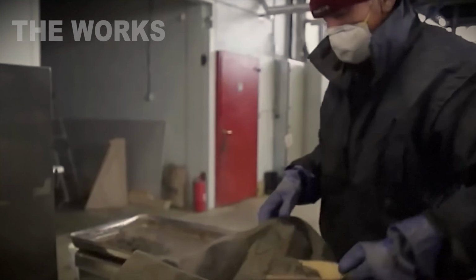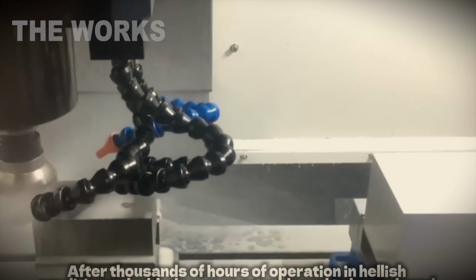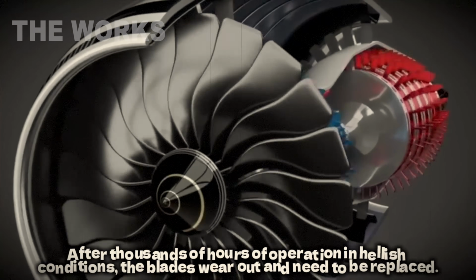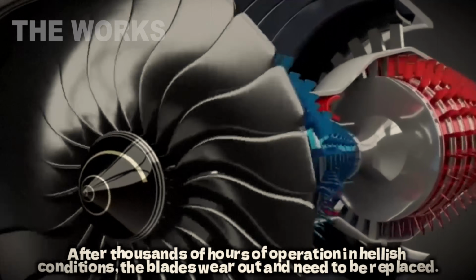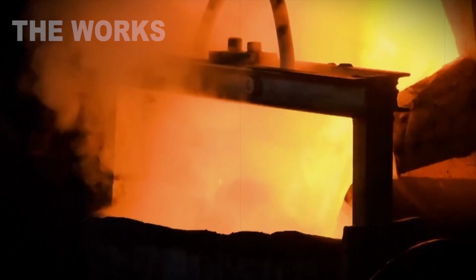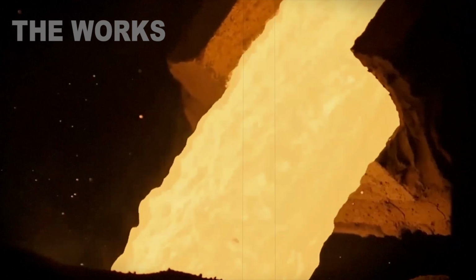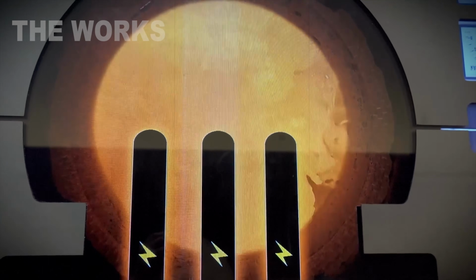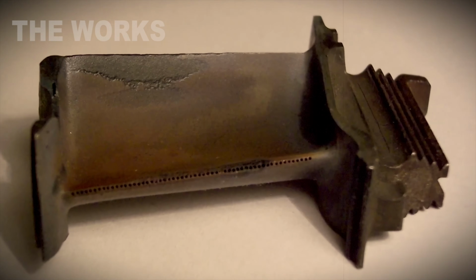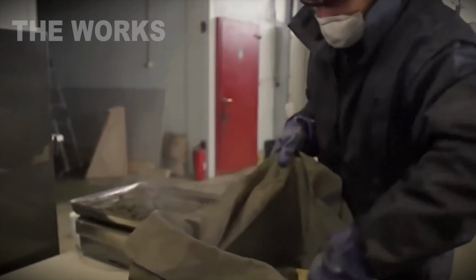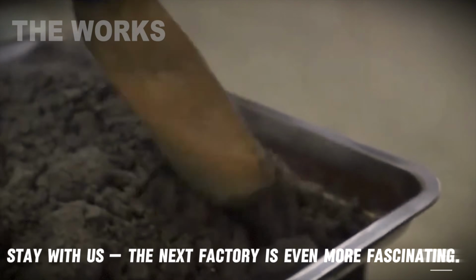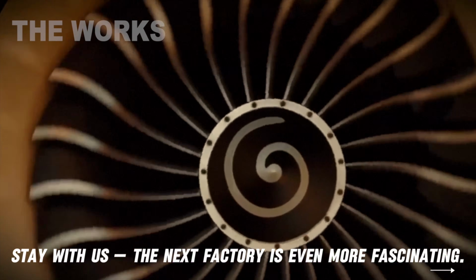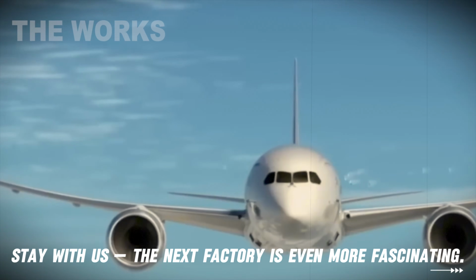Recycling rhenium from spent blades is mission critical. After thousands of hours in hellish conditions, blades wear out and get replaced. The old ones don't get tossed, they're melted down, rhenium and other precious metals extracted, and used again. Around 30% of rhenium comes from recycling, more than most other metals. And the reason's simple. At these prices, nobody can afford to throw rhenium away.